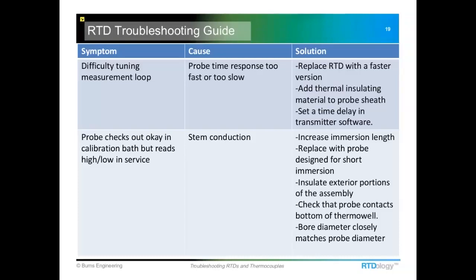And you'll get conduction along the lead wires and the probe sheath or the thermal well. In a case where the process is higher than ambient, it's going to have a little bit of a cooling effect on that sensor, so you're going to read too low. A freezing process is going to be the exact opposite. So some ways to resolve this would be to try a different style probe that can get you more immersion length. If it's possible to put insulation around the sensor and the piping on either side of it, that can be a real easy way to fix it.